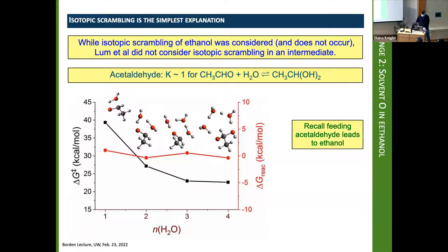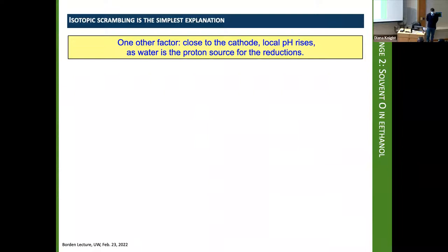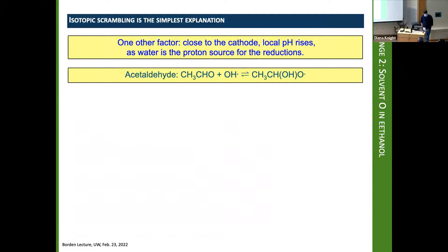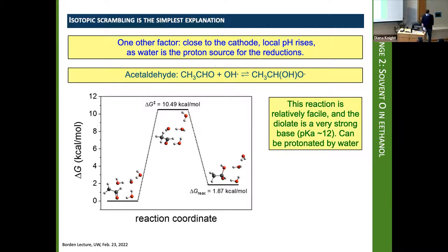Then one more thing, remember the local pH. We are busy consuming protons that come out of water making hydroxides. So we've got alkaline conditions. So we won't necessarily have to even use water. We could use hydroxide, and we could then make the conjugate base of the diol. And that is not only a quite facile reaction, but the diolate is a very, very strong base. It'll be readily protonated by water, and then the reverse reaction will take you back to acetaldehyde with oxygen-18. So anyway, we think that was probably what was going on.